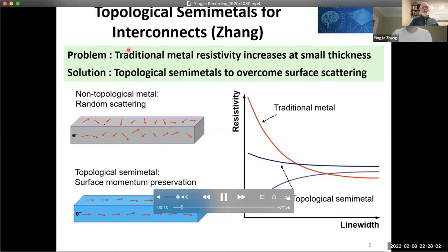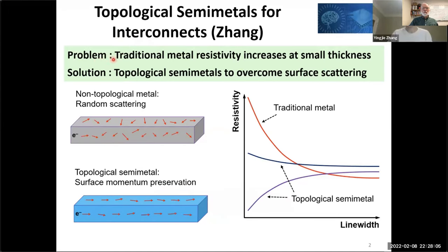All right, we propose to use topological semi-metals for applications as electrical interconnects. So the problem with traditional metal interconnects is that the resistivity increases a lot as line widths become smaller down to the nanoscale. And that's due to the random surface scattering effects in these materials. So to overcome this problem, we propose to use topological semi-metals. And these materials have special surface momentum preservation effects. As a result, we can still achieve very high mobility surface states, even when we make them into nanostructures, and when these structures have lots of defects.